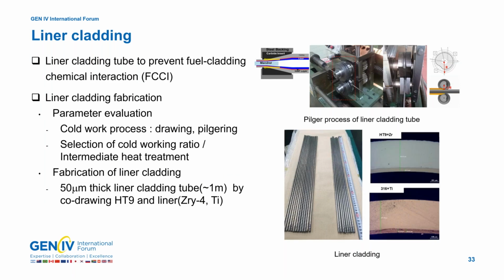And for a stronger barrier, we worked on the liner cladding. So not electroplating of chromium. This one is another thin tube barrier, like the liner of zirconium or titanium, about 50 micron thickness. The liner was fabricated by co-drawing and pilgering steps. We fabricated the liner cladding about 1 meter in length with two different liners. So we are working on this process also.